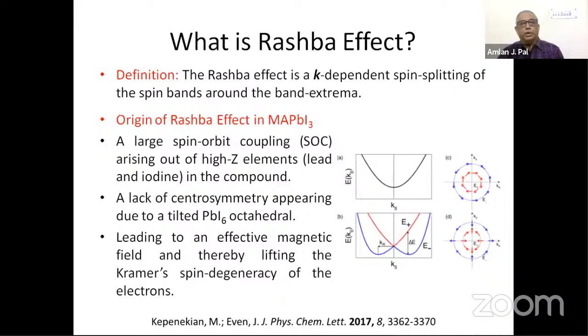Because we have a large spin orbit coupling because of the high Z element, that is lead. Lead and iodine both are high Z elements. So we have a large spin orbit coupling and lack of centrosymmetry arising out of the tilted PbI6 octahedra. We talked about the structure, and these PbI6 octahedra are tilted, so there is a lack of centrosymmetry. Because of this, there is a kind of effective magnetic field, and thereby the lifting of the Kramers spin degeneracy of the electron. And because of that, it was theoretically proposed that the bands will be spin split, both the conduction band and the valence band.